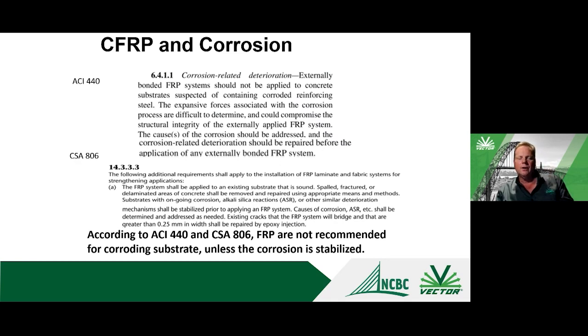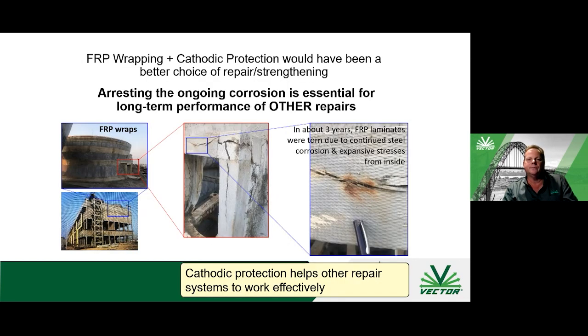Another thing just to point out for durable repairs is that carbon fiber or FRP strengthening is being pretty commonly and successfully used for strengthening of structures. And the ACI committees basically say that if you're going to be strengthening a structure, the strengthening system relies upon the bond of the FRP to the concrete to transfer the load. So there's an encouragement to look at whether it's actively corroding, and if so, what can you do to address it?